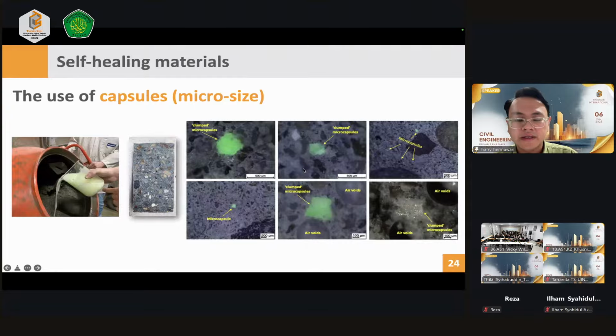Here, this is a picture that I took during my PhD research. So we developed the microcapsules in slurry condition, but at that time we added a color pigment to the microcapsules. Because of what? Because when we put the microcapsules in our concrete mixture, and when the concrete gets hardened at a later age, we can inspect what the condition of our microcapsules will be. For instance, this is the picture of the microcapsules which are available in my concrete matrix, and they glow under UV light. So we add a color pigment like fluorescein, so the microcapsules later will glow in the dark.